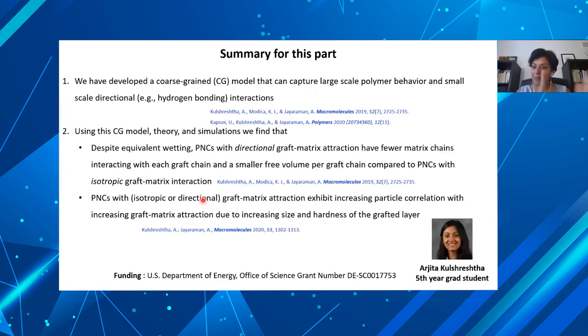So I want to summarize this part before I move to the second part. I wanted to show you a coarse-grain model that we developed. That phenomenological coarse-grain model mimics a large polymer behavior because it's a long chain with localized directional interactions. And we found that if you use that type of chemistry in composites, you can get similar matrix-graft wetting for the directional and isotropic. But even if it's equivalent, your chain-level contacts and free volume are different for the directional and isotropic. They both lead to increased pair correlation functions between particles. And as you increase the attraction strength, because you have more wetting, particles get larger and harder and show higher correlation because of depletion-like effects.